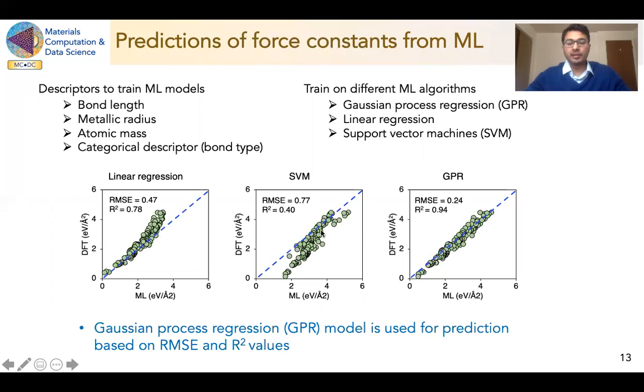So these 3 figures show the predictions results of unseen data. So unseen data meaning the predictions of force constants of rhodium and iridium element. These 3 plots are from the different machine learning models, and you can see that the performance of GPR Gaussian process regression model is better compared to other models with RMSE 0.24 and R square 0.94. So we use a GPR model for the predictions of force constants.